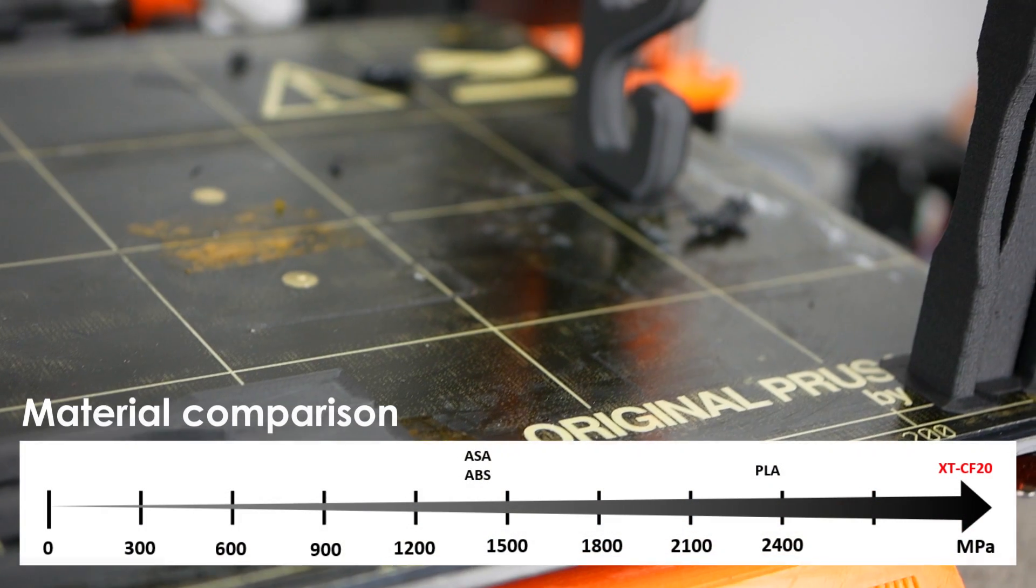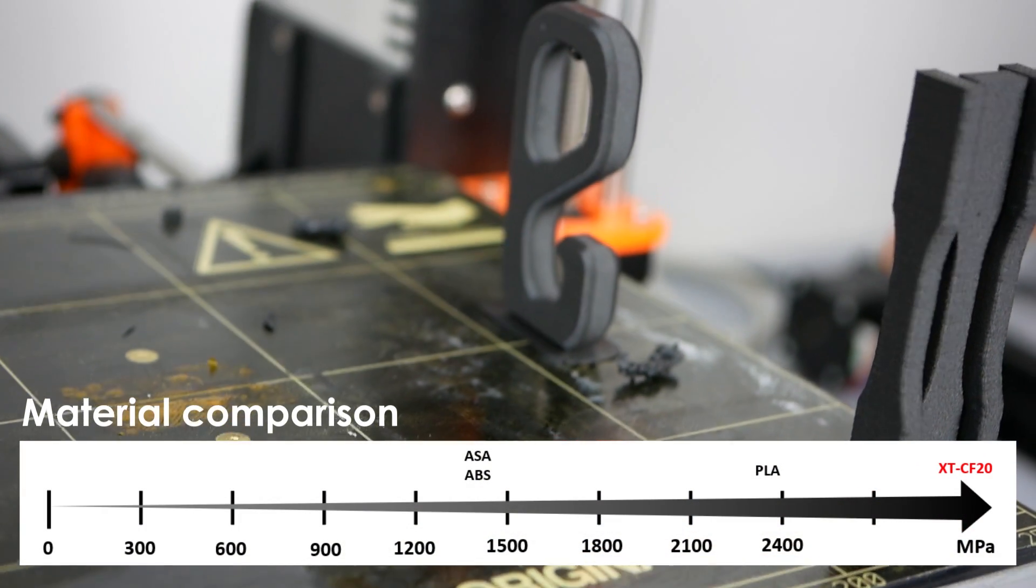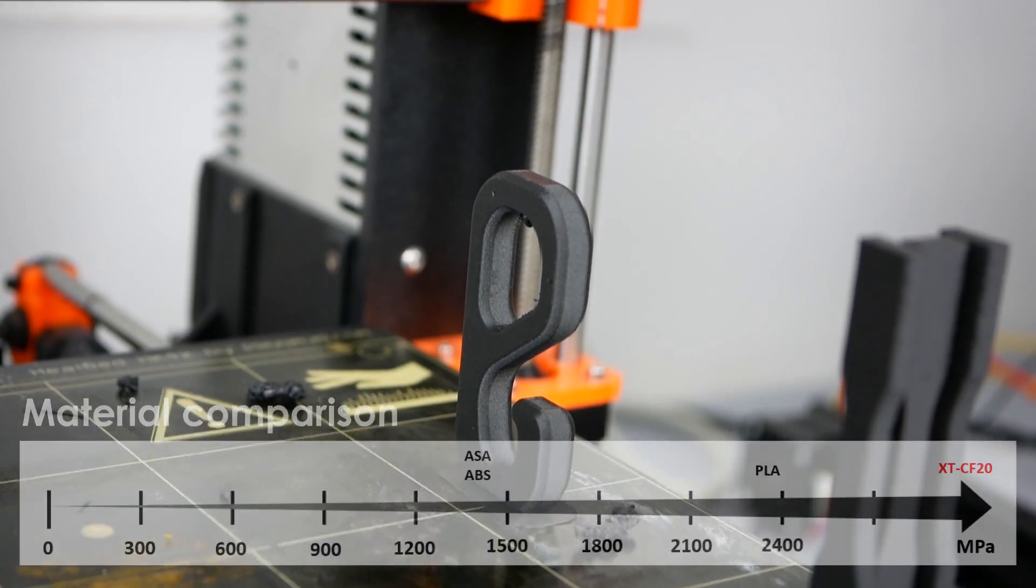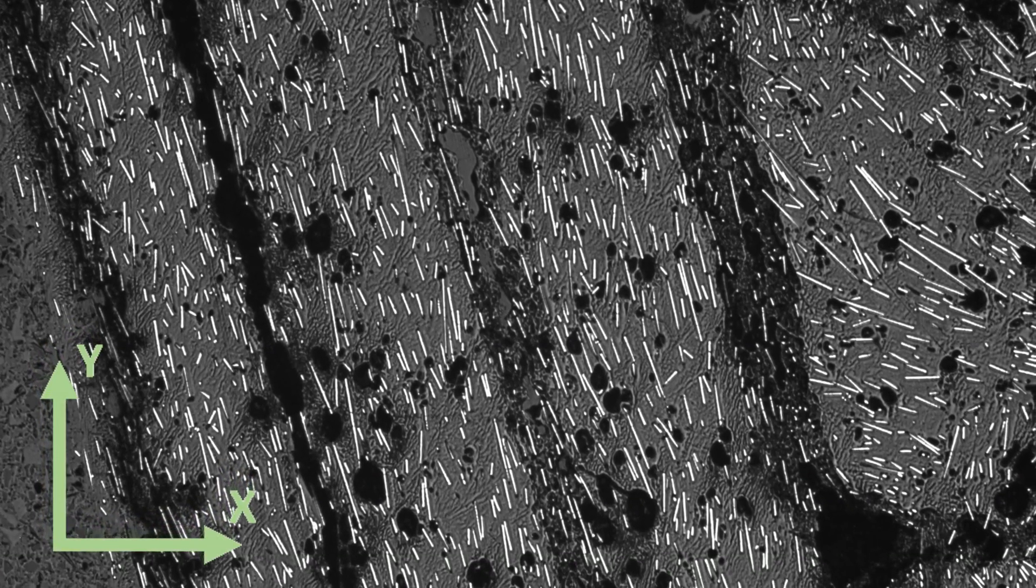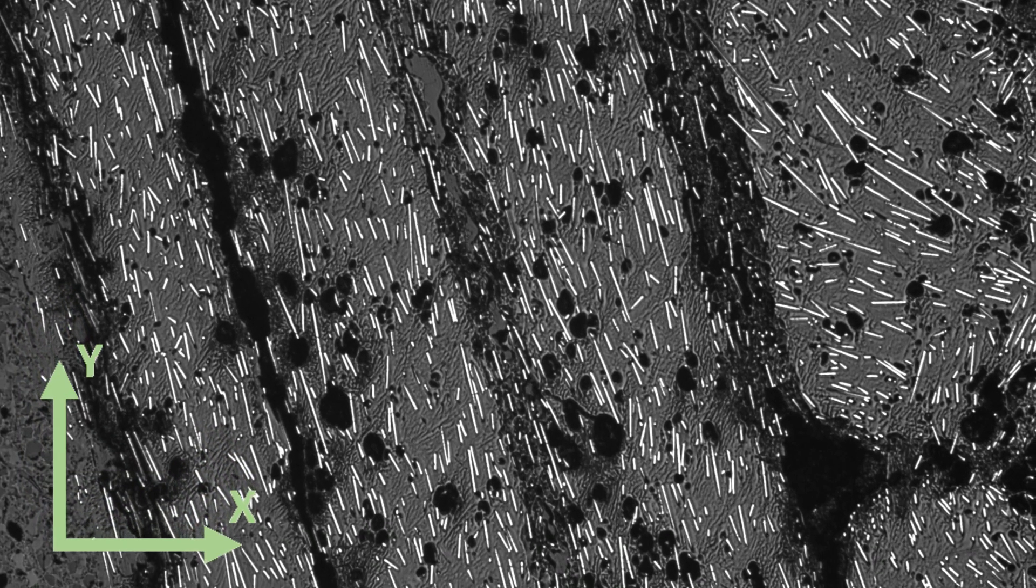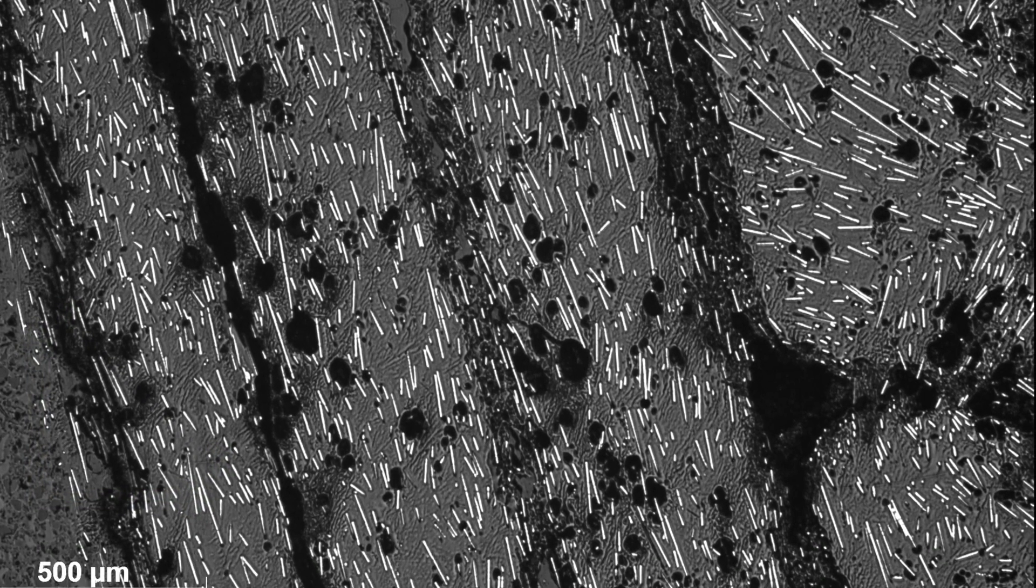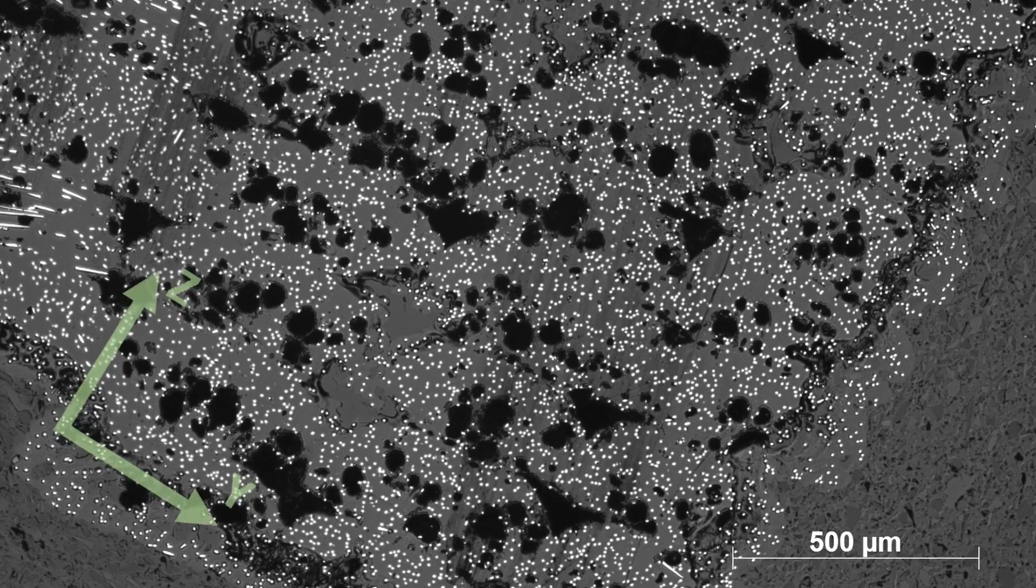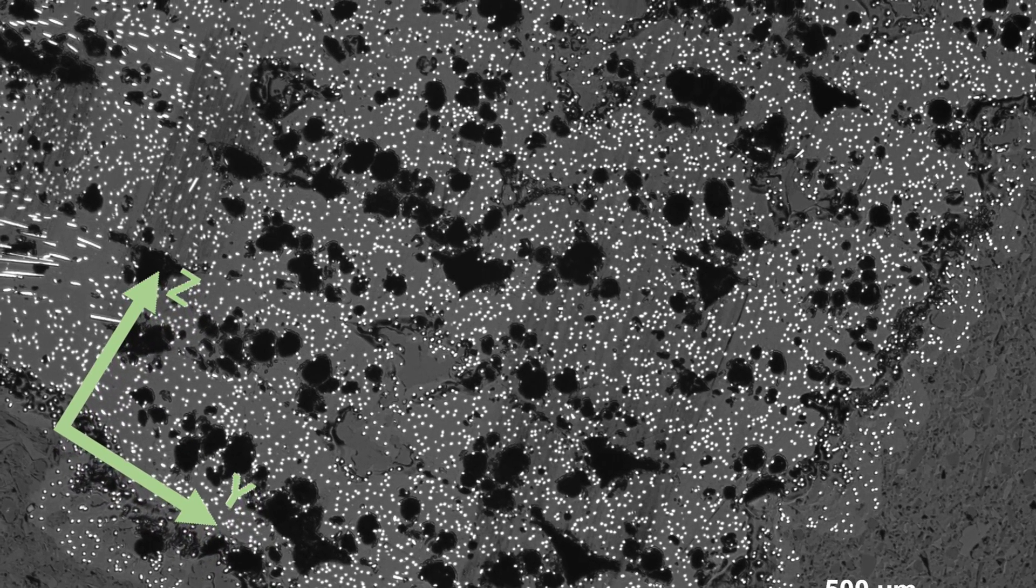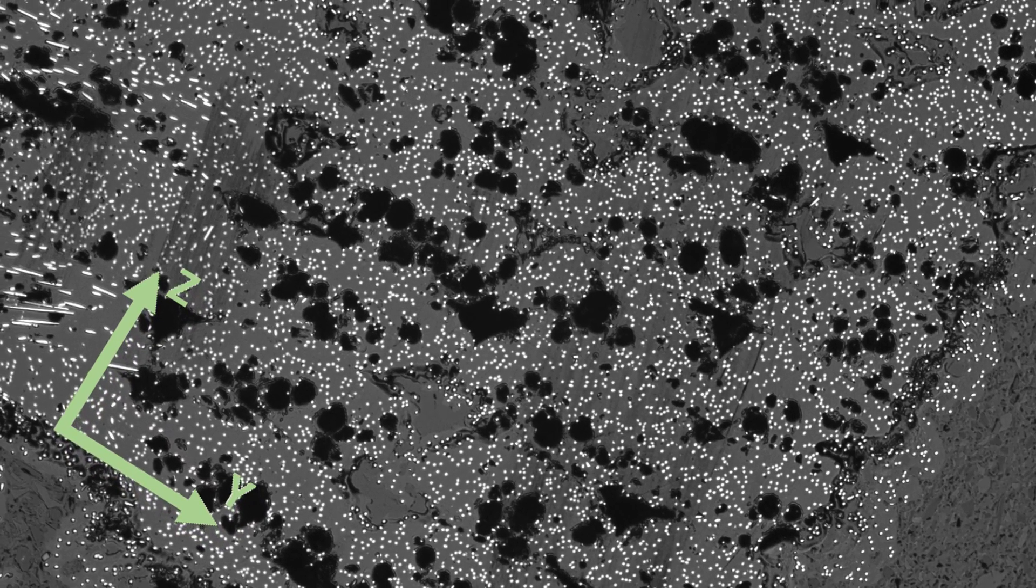This is the first time when I also tested the stiffness perpendicular to the printing direction, so the upright specimens. If we take a look at a microscope shot of the material, we see that the carbon fibers orientate themselves in the printing direction, and these fibers give the material its superb rigidity. Perpendicular to the printing direction, they are only barely adding strength and stiffness.